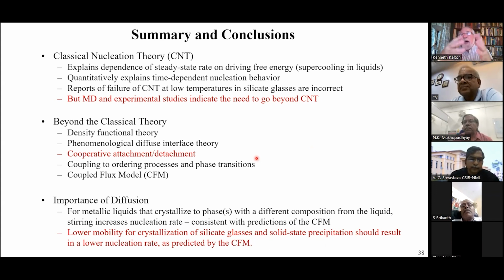Yes, I think so. I think that all of the questions, however, about the interface and about the thermodynamics, the kinetics, would have to be examined because, again, you've got a dense solid forming another solid. So it's quite possible you could have some problems with a hopping mechanism there as well. And also, if you ended up having a different composition, then you're also going to have long-range diffusion effects potentially. We normally think about that for growth, but at least the calculations I presented indicate that it could be important there as well. So I think this is a wide open field.